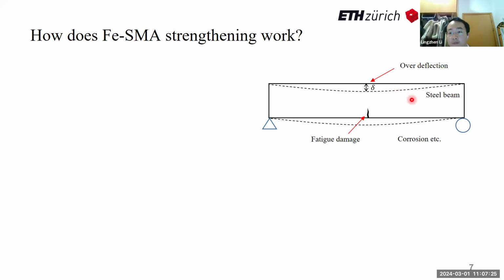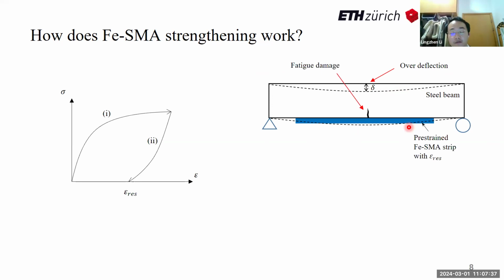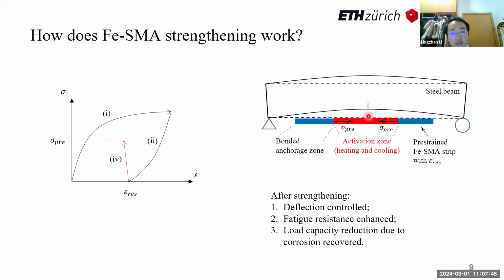As we previously mentioned, for existing steel structures, problems would exist. But if we bond a pre-strained shape memory alloy, which is stress-free, to the target location and heat its center part, it tries to shrink, if you remember the shape memory effect. However, the parent structure limits its deformation. Therefore, tension is generated in the shape memory alloy. To balance this tensile force, a compression is generated in the parent structure. This compression would help us to close the existing crack in the existing structure. Not only can this technique improve the fatigue and structural performance, but it can also do deformation control, etc.